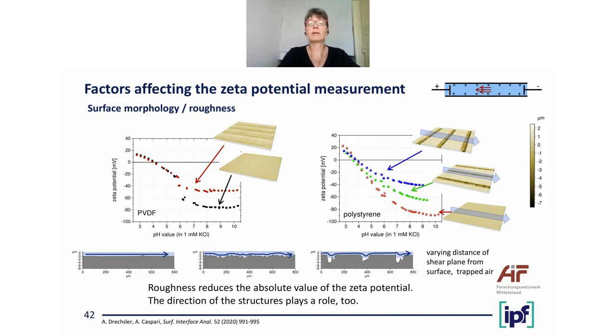So in the left example, we studied PVDF polymer surfaces with different roughness, and you see that the absolute amount of the Zeta potential is smaller if the surface is a little bit rougher. On the right-hand side, we did a study with polystyrene foil in which we applied some scratches or trenches, and here you can also see that the apparent measured Zeta potential values become smaller if you have these scratches in the surface, and it also depends on the direction of the scratches.